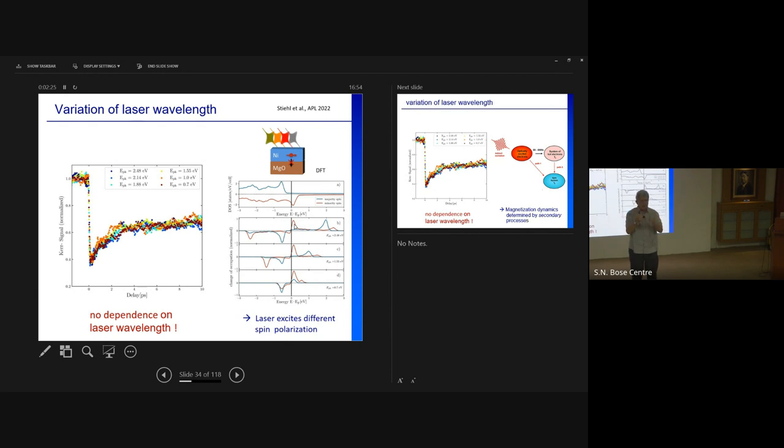Okay, the lifetime of the electron is spin dependent, but that is not the coherence time. The lifetime is spin dependent because a minority electron has more states it can decay into than a majority electron. And I measured them. But it's not the coherence time; I would say the coherence time is the same. But the ballistic transport depends not only on the coherence time, it depends on the effective mass. And the theoretician explained it this way: you have an s electron for the majority electron and a heavy d electron for the minority. If you really can believe that, I'm still a bit concerned, but that's how it works. I worked on Fermi liquids, I have to believe that. Yeah, we have to believe it somehow.